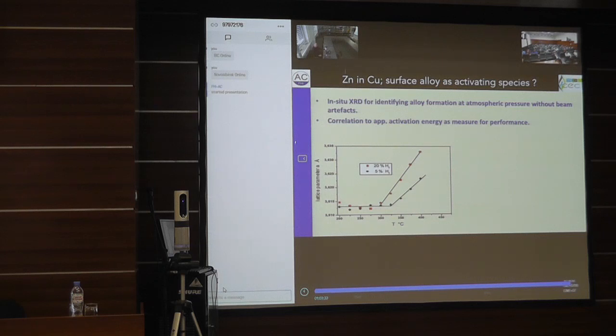And interestingly enough, you see simultaneously that the Arrhenius parameter also increases. That means brass is not a poison. Brass also can synthesize methanol, but this is not as effective as the combination of zinc oxide with lattice defects in it and with copper metal that has oxygen in it. That's interesting because you would say this is a semantic difference. Copper plus oxygen and zinc oxide with defects, is this so different from brass that has a little bit of oxygen or the surface oxide layer? And the answer is yes, it is different.